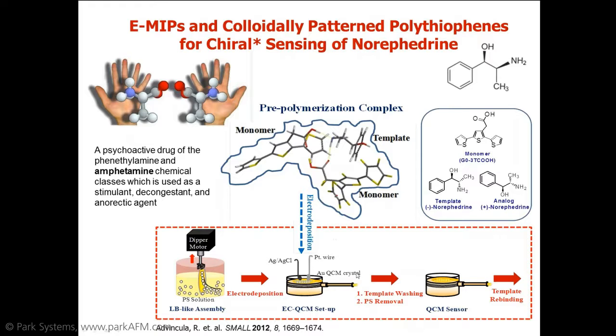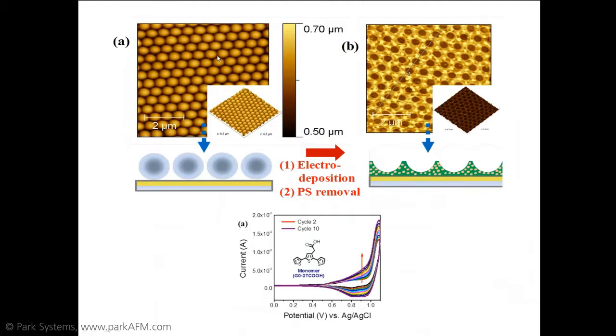Well, we employed, again, quartz crystal microbalance and templated or molecularly imprinted our way towards the detection of the right norepinephrine stereoisomer. We utilize this arrayed film as shown here. The idea is once we molecularly imprint the norepinephrine, it will create cavities along this film, and as you can see, we should have an increase in the surface area that's exposed to the analyte and the film. And then, of course, a layer that functions as your transducer system.